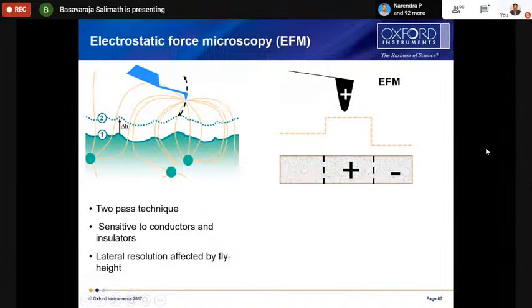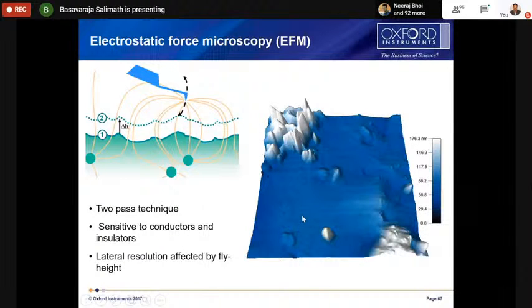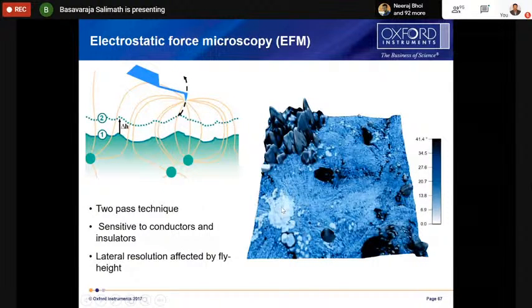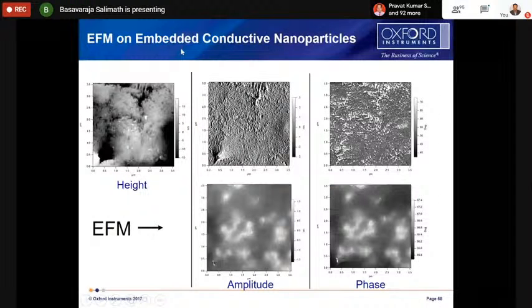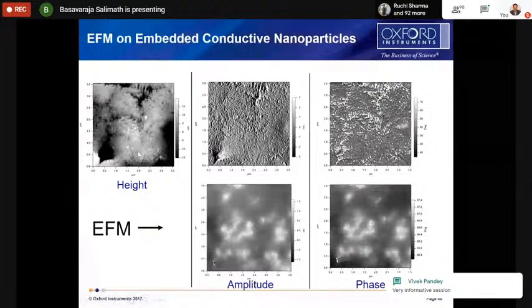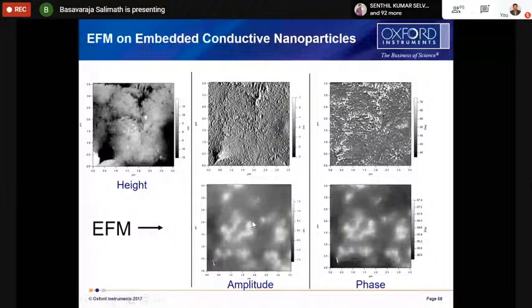Like that, this is actually a morphology image, and you can see these are some static charges. This kind of static charge study we can do with an EFM. And this is one example, where some conducting nanoparticles are embedded inside this sample. You can see this is the morphology, and this is the normal amplitude and phase image. We cannot see these embedded nanoparticles inside. Those are conducting actually. With an EFM, we can see where those embedded nanoparticles are, which we can see with this electrostatic force microscopy.